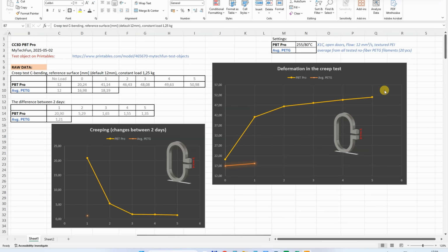This is the distance between two reference surfaces, and this is the creeping, the difference between 2 days. And we can see that it reduced after day 1, but it was constantly there even on the 5th day. And it was huge compared to any material, not only PETG.